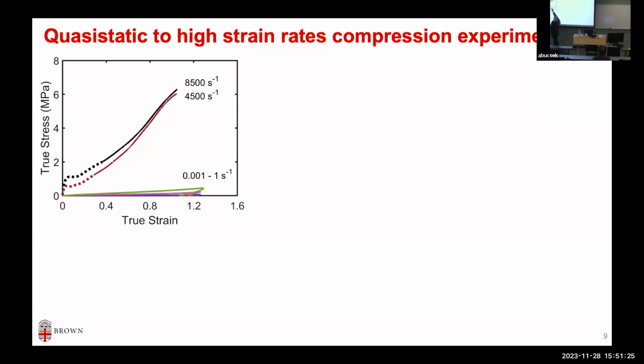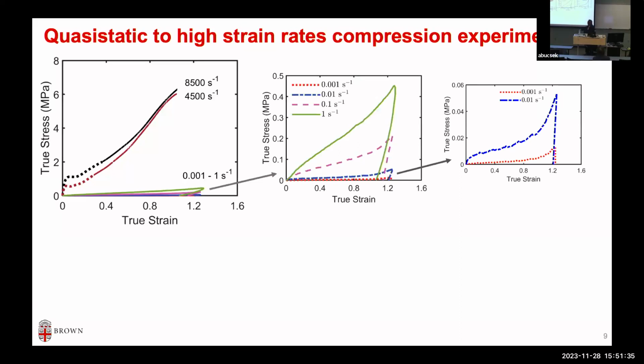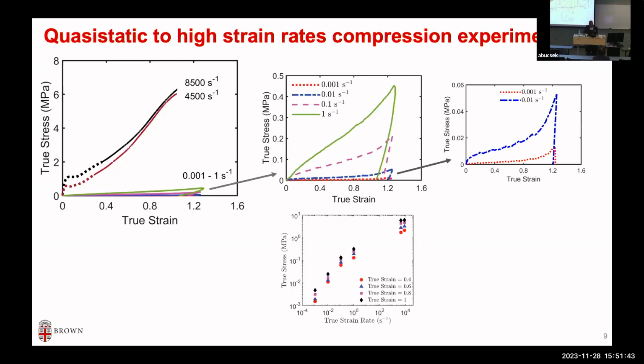Very rate dependent. Move from very small strain rate, 10 power minus 3, all the way to 10 power 4. Highly rate dependent behavior. If I zoom in on that small area and the quasi-static, you can see very drastically rate dependent behavior with very interesting loading and unloading curves, right? And so on. I can take any strain value, and strain rate versus stress shows highly strain rate dependent behavior, which you already saw in the qualitative experiment. This is a quantitative behavior. A model should be based on these technical data and it should be able to represent that, in one dimension.